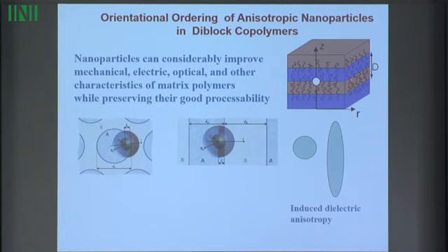And what is interesting about these block copolymers from the physical point of view is that this system is anisotropic. So say lamellar phase is geometrically anisotropic. But for example, dielectric anisotropy, optical anisotropy, is very, very small. And the reason is that it's only geometrical anisotropy. Within each block, the material is isotropic. So there is some very small contribution coming from the surface area.